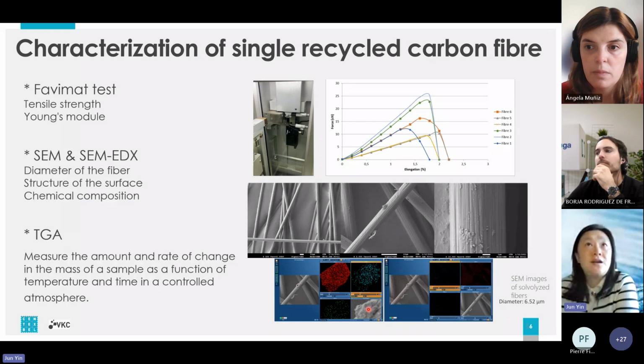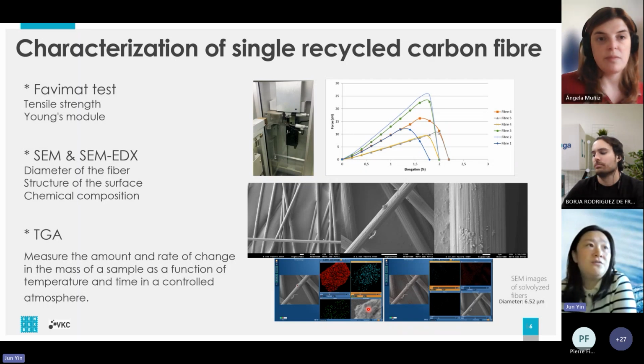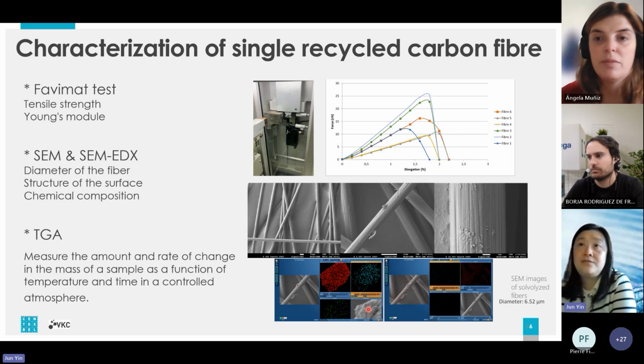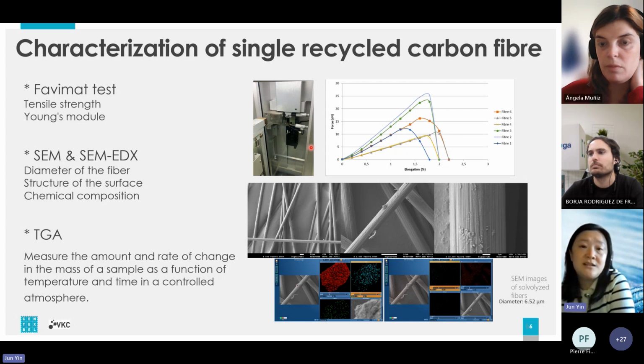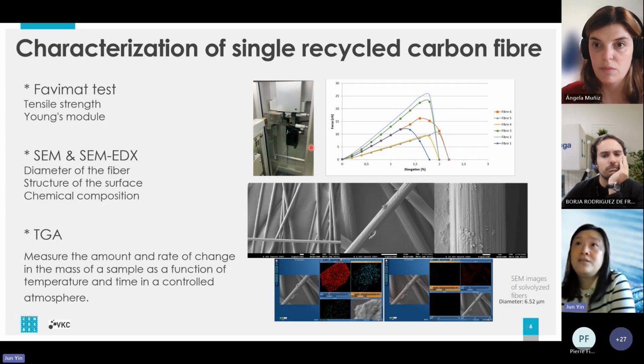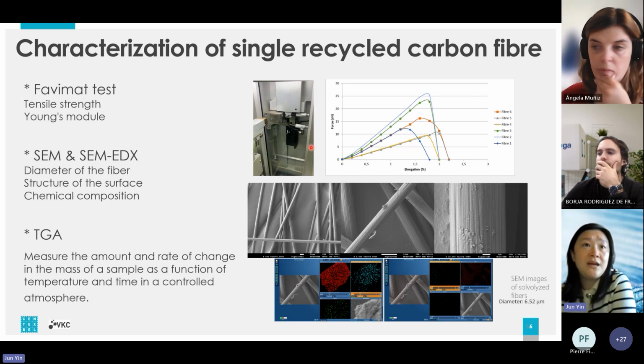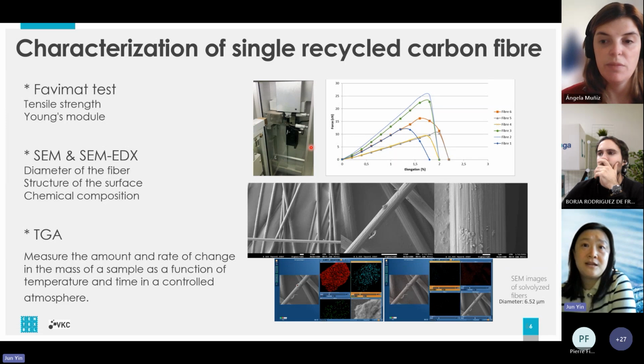So we use 3 different characterization methods on these single carbon fibers. The first is the Favimat test. It's a kind of tensile test, but on single fibers. If you look at this photo, on this machine we can measure the linear density of the carbon fiber, and we can obtain the force as a function of elongation, so we can estimate the tensile stress and Young's modulus of this fiber. Of course, with SEM, we can measure the diameter, the surface structure and chemical composition by SEM-EDX. And by using TGA, we can measure the amount and the rate of change in mass of a sample as a function of temperature and time in a controlled atmosphere.